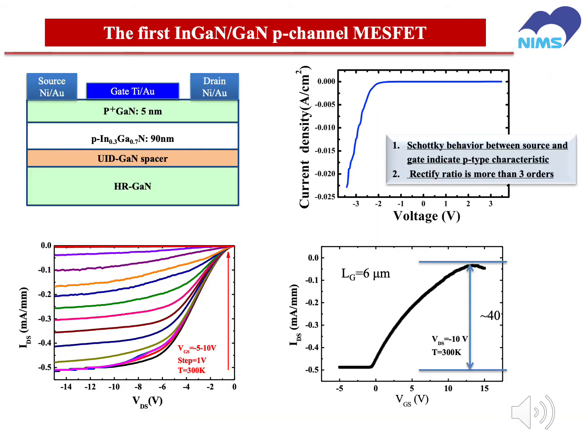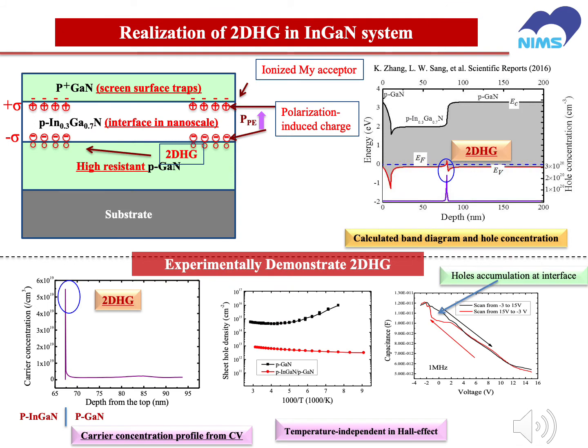device application. Our group fabricated the first InGaN p-channel FETs, and this p-channel FET utilizes the InGaN heterojunction. This device shows a very good rectifier ratio of more than 3 orders, and a very good FET performance. The good performance of the p-channel FET is from the realization of the two-dimensional hole gas at the InGaN/GaN heterojunction. The nitride semiconductor has a very unique polarization field. The spontaneous polarization and the piezoelectric polarization can generate the two-dimensional electron or two-dimensional hole gas at the heterojunction.